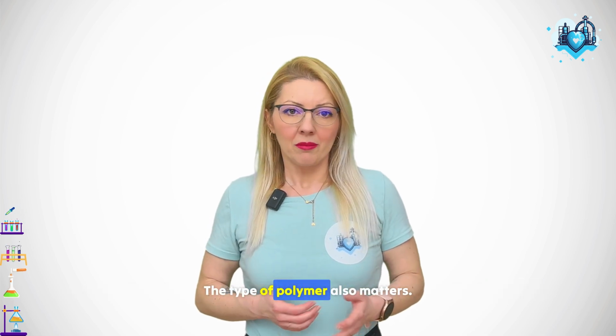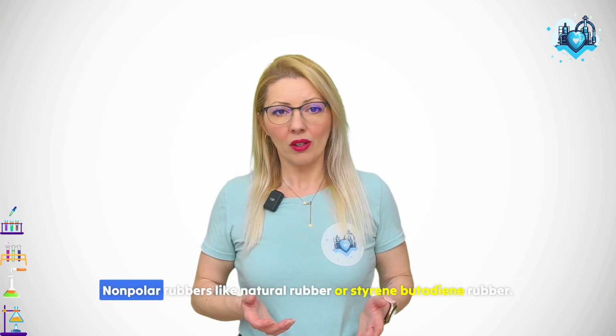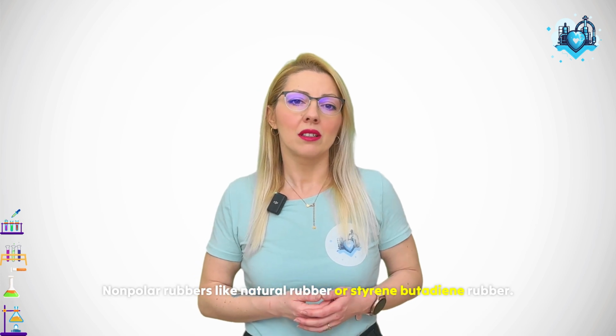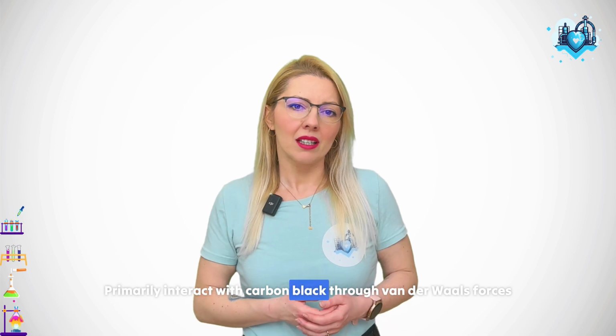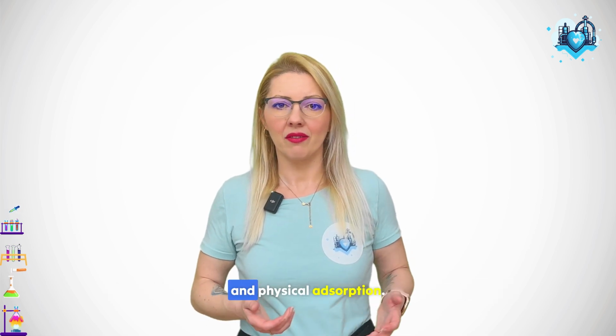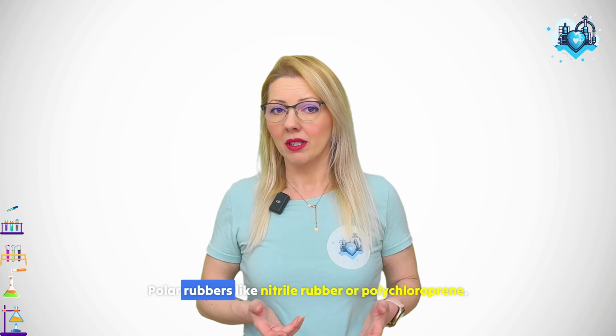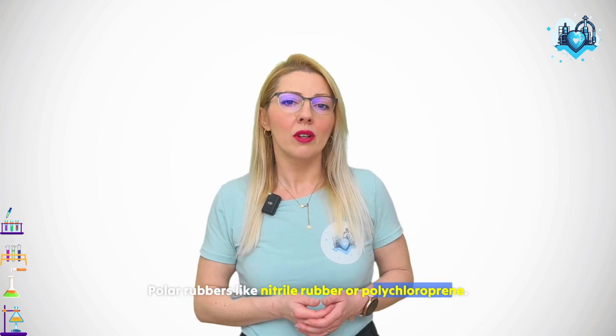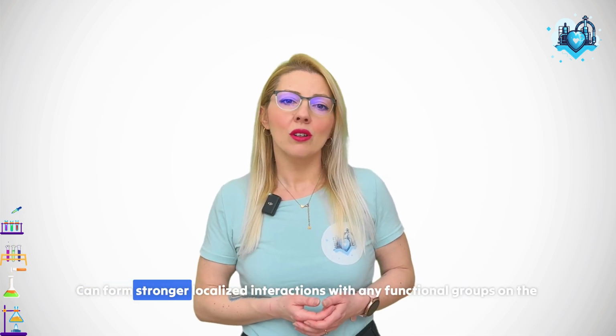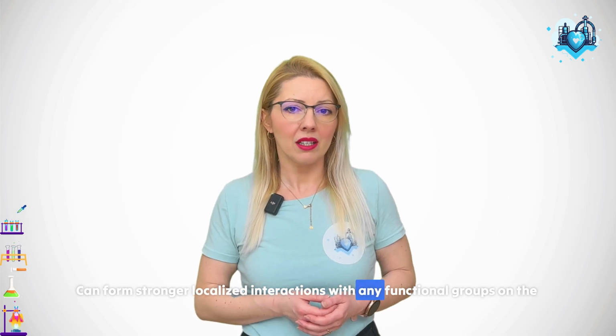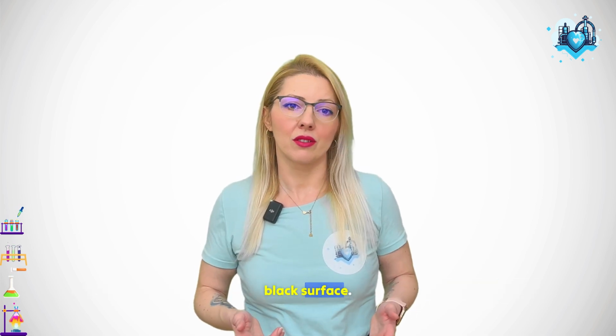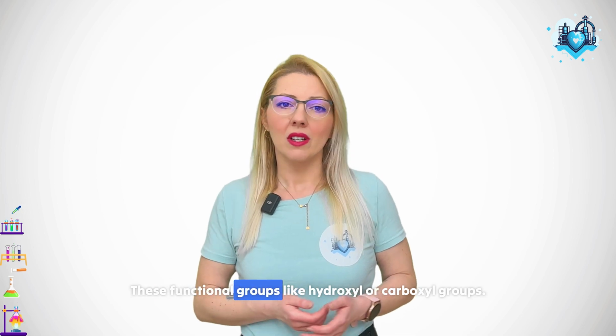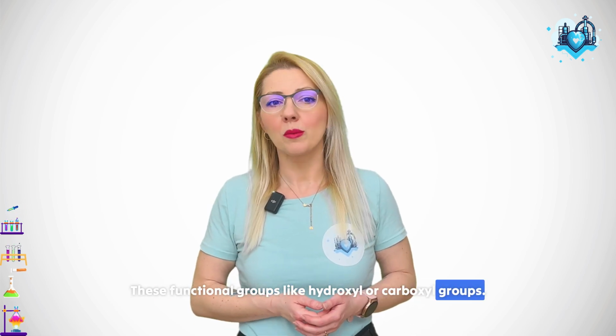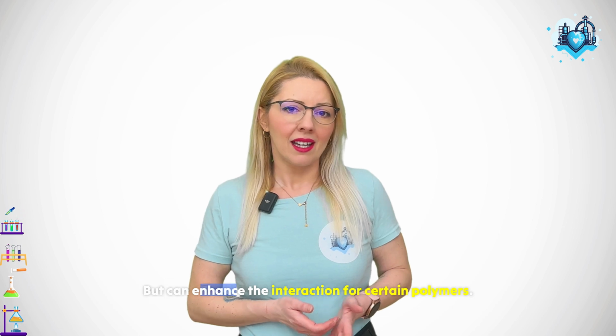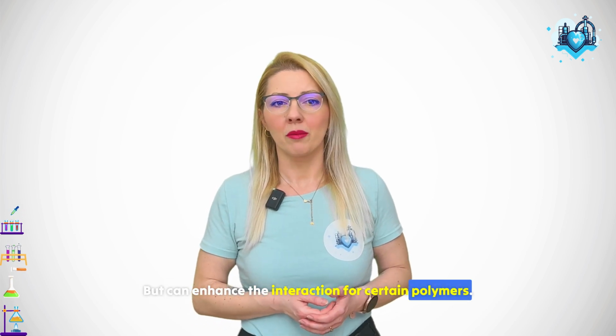The type of polymer also matters. Non-polar rubbers like natural rubber or styrene-butadiene rubber primarily interact with carbon black through van der Waals forces and physical adsorption. Polar rubbers like nitrile rubber or polychloroprene can form stronger localized interactions with any functional groups on the carbon black surface. These functional groups, like hydroxyl or carboxyl groups, are minor but can enhance the interaction for certain polymers.